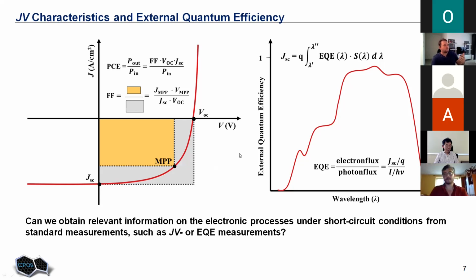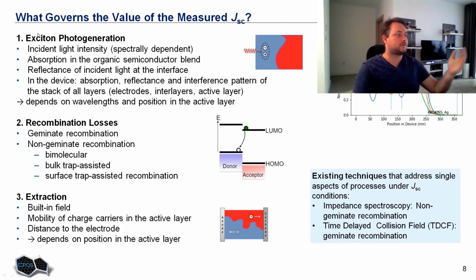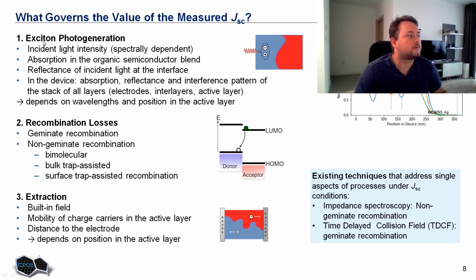And that's why our approach is to find a possibility to use this information, which is minimum required experimental data, in order to get as much quantity of information about recombination processes and charge extraction in a solar cell as possible. So for this purpose, we need to consider three equally important processes of operation of solar cells. First, we need exciton photogeneration, and that will be happening in this active layer between electrodes, and distribution of this optical field will define where and how many charge carriers we will generate.